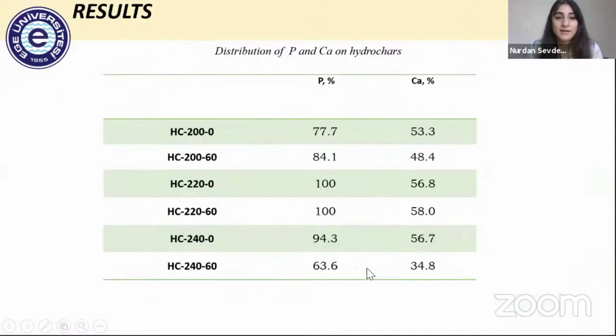So here you can see the distribution of phosphor and calcium on char. In hydrothermal carbonization, generally, most of the inorganics in biomass go to the process water. However, in our case, most of the phosphorus and calcium in poultry litter remain on the char instead of the process water.